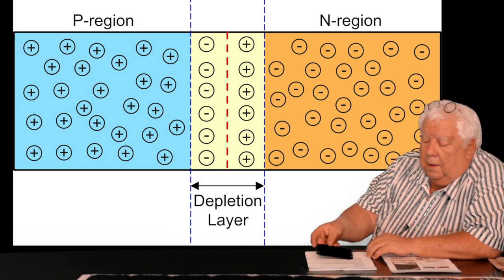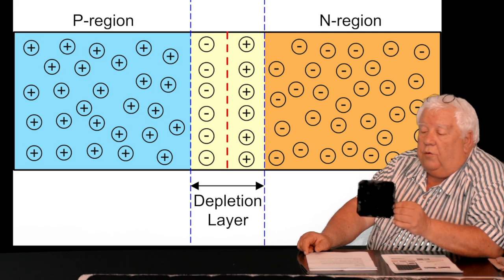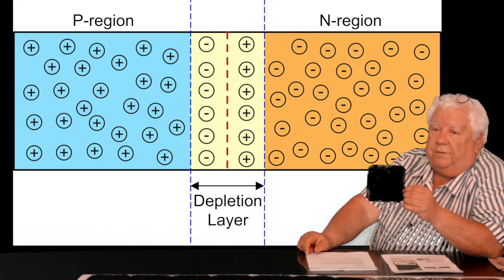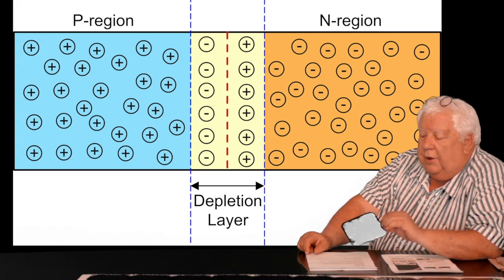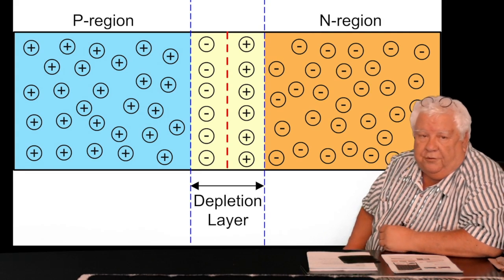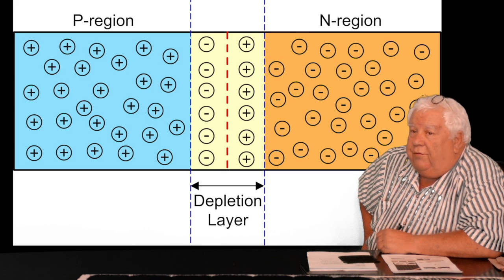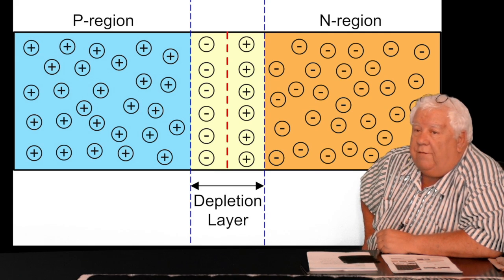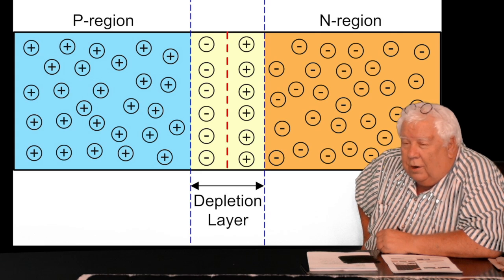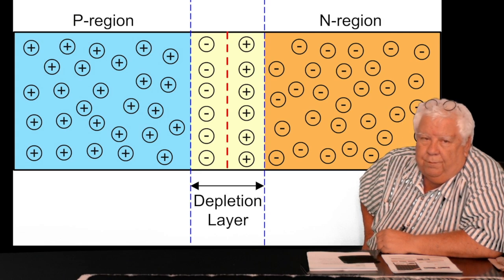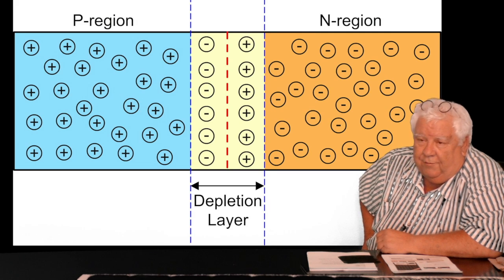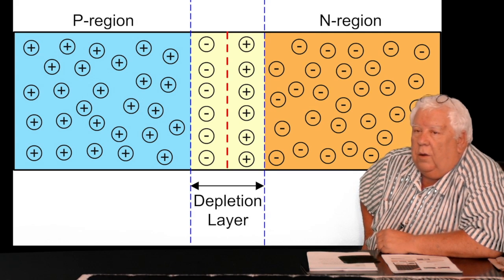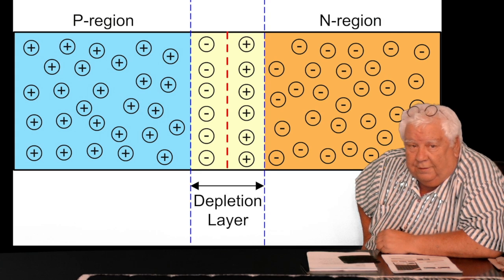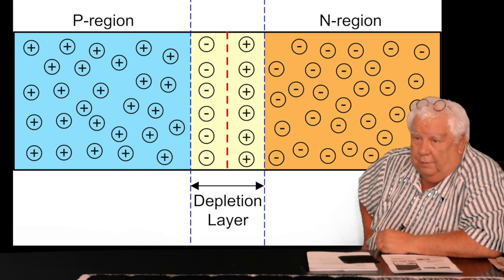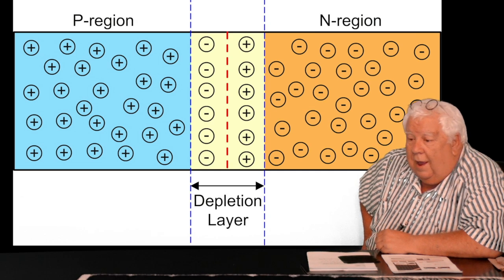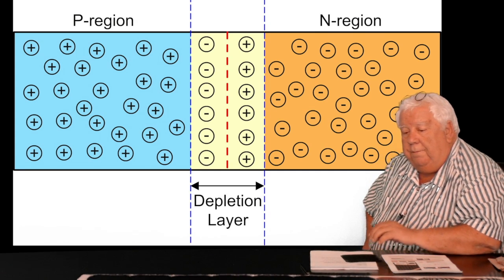If we do no current flow, our open circuit voltage on this particular SunPower Maxeon cell is 0.687. Now that's because this is a 125 millimeter by 125 millimeter cell, 5 by 5 inches. And you get about 1/4 of an amp a square inch. So if we made this the size of a football field, it might do 500 amps. But by the way, it's still going to do it at 0.687 volts. The voltage is never going to go up. In full sunlight, it's 0.687, and in full darkness, it's about 0. And that is what a solar cell is.